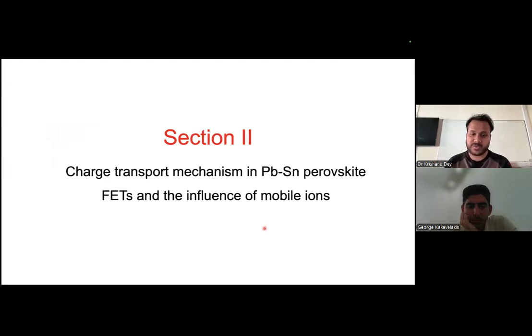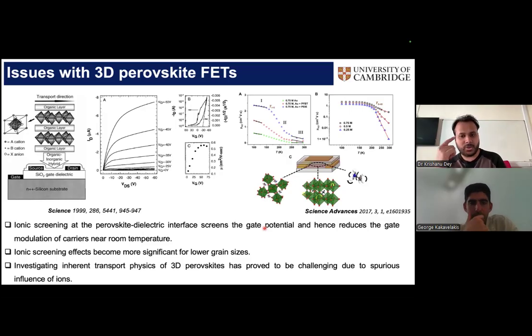And then we wanted to understand how the charge transport happens, and if there is any influence of mobile ions in these devices. The reason for looking into that is that 3D perovskite FETs have been worked on for at least a couple of decades now. The problem is that when you apply a voltage at the gate terminal and you are trying to induce, let's say, negatively charged electrons, the iodide ions are also mobile, so they can get attracted towards the interface. Those ions can then shield some of the applied voltage and screen it from getting applied on the electrons. That is why the effective voltage applied on the channel is far reduced. Therefore, as you go to higher and higher temperature, where ions can move much faster, you reduce the mobility. That's a trend that's been seen in many papers. So the mobility decreases as you go to higher temperature, and this is believed to be due to ion migration or ionic screening effects.